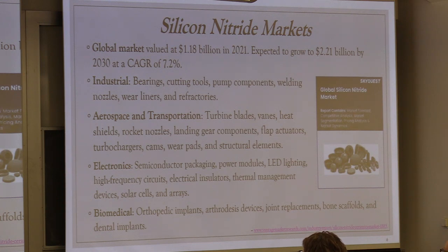But there are also cutting tools that are an important part, and other wear parts. In aerospace, it's also really bearing components and various actuators. They take advantage of the weight difference that silicon nitride has. So every modern-day airplane that you fly on, the flap actuators actually have silicon nitride parts in them. All of the bearing components and the rods and push rods and everything else. It's fairly low stress, but quite an effective operation for silicon nitride. Semiconductors are expected to be a high growth area for silicon nitride, particularly associated with power modules. And in biomedical applications, the only product that's really been approved or cleared by the FDA at this point in time has been spinal spacers, which I'll talk about a little bit later on. But there are significant developments in a whole lot of healthcare-related areas.